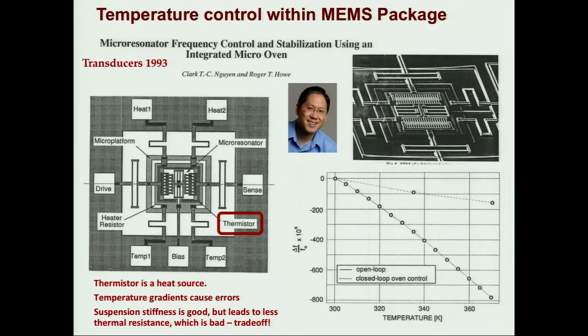So the MEMS community has been talking about OCXOs a long time. This is some stuff in Clark's thesis more than 20 years ago. Polysilicon MEMS resonator, suspended on a little silicon island by some tethers that brought the electrical signals, the thermal isolation, and the mechanical support. And he had a thermistor on the suspended element. He could measure the temperature of that. He could apply different amounts of heat to the suspended element to try to regulate temperature in a fixed range and overcome the dominant sort of 30 ppm per degree C temperature coefficient of the silicon, and did quite well.